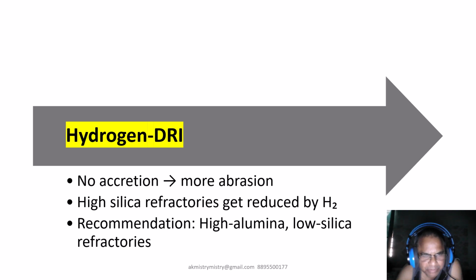As accretion gives protection in coal-based DRI, here that protection is absent, and that is the reason for faster abrasion in hydrogen DRI.